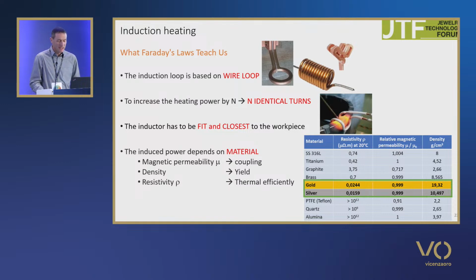And the induction effect depends on the materials. As shown, stainless steel, titanium, graphite are very good candidates for induction heating. The poor resistivity of gold and silver is a problem, but they are very high density materials, so it is possible to heat gold and silver metal. In this table, I show you PTFE, Teflon, quartz and alumina. They are widely used in holding and enclosure systems for induction. Due to their very high electrical resistivity, they are not affected by the induction effect.